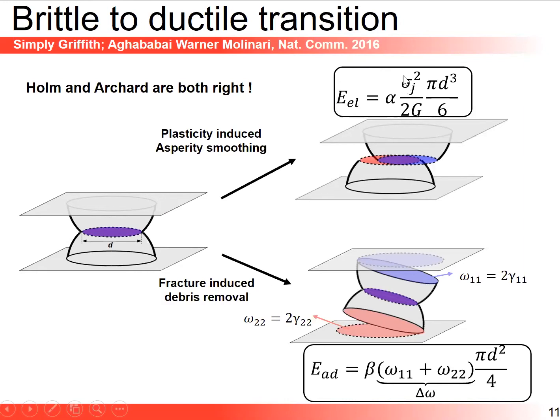The elastic energy density is the strength that the junction can carry, sigma j. You cannot go above sigma j because it will flow plastically. So sigma j puts a cap. Sigma j squared over twice the shear modulus is the elastic energy density, and I'm multiplying this by the volume of the two hemispherical asperities, so d to the cube. So you store elastic energy, and you may use this.